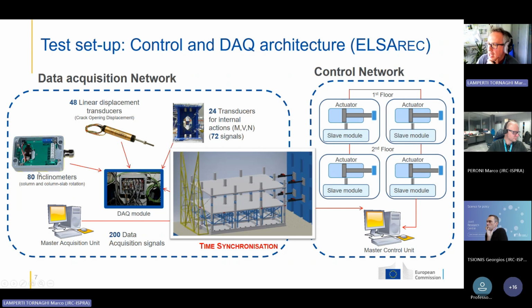We used 80 inclinometers to measure the inclination of the column and of the slab, 24 transducers for internal actions, bending moment, shear, and axial load, and 48 linear displacement transducers to measure the cracking within the slab. All this data gives around 200 data acquisition signals that are synchronized together with the actuators used to stress the building during the test.